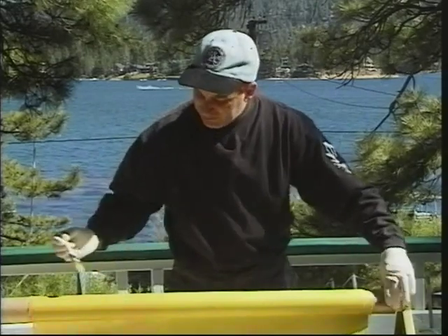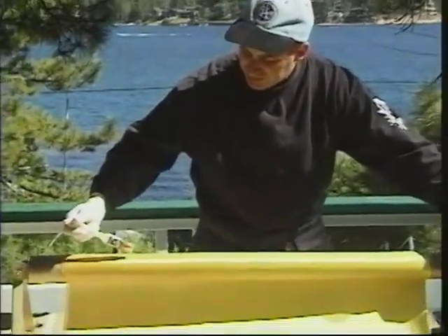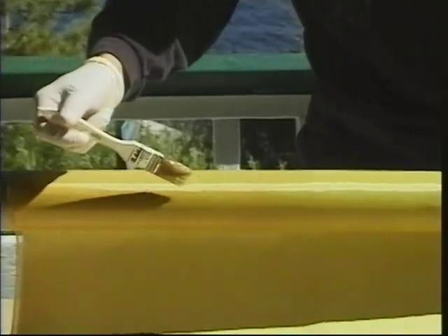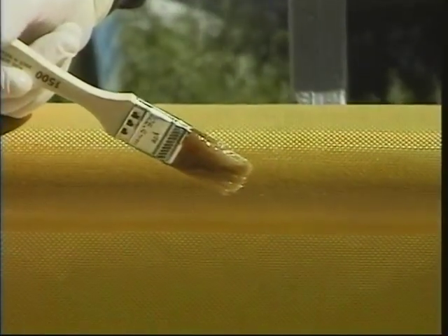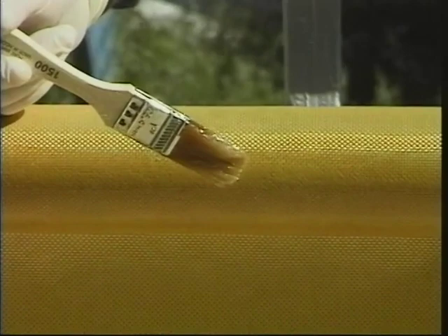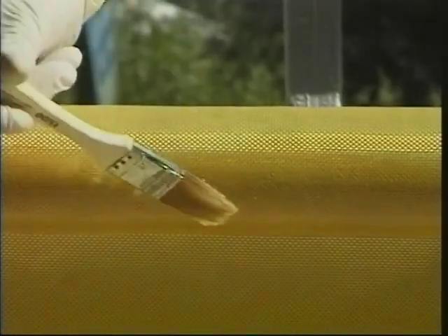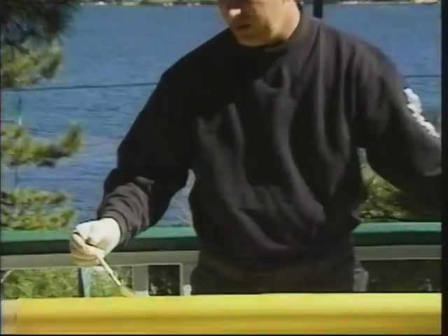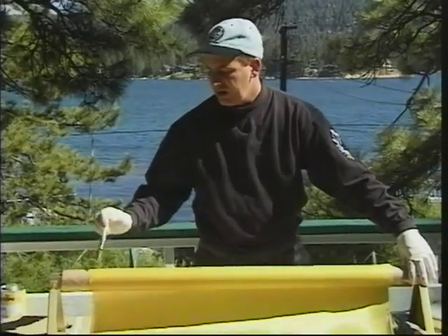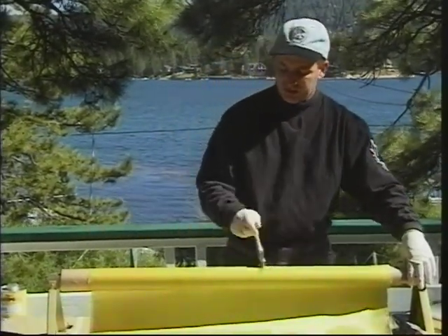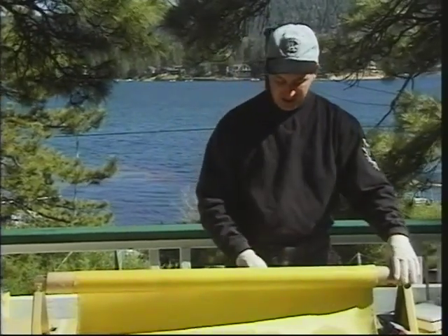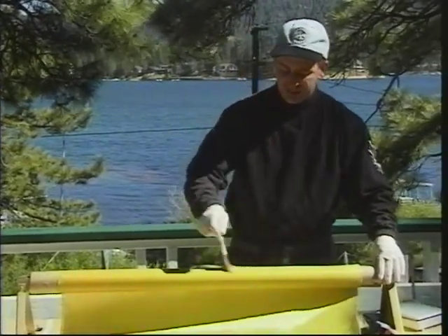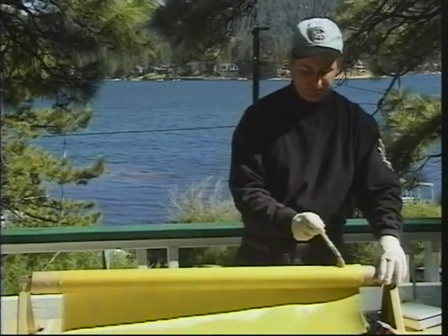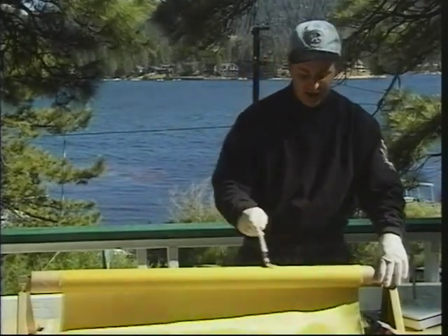Now, if we could just zoom in on this area right here, you can see Kevlar wet out. It does darken somewhat as you wet it out. This is not wet out, this is wet out. And so it becomes a little darker hue of gold as you wet it out. When in doubt with Kevlar, use more resin, especially if you're going to be compacting it later with the heat tape, because you'll be bleeding off any excess resin.